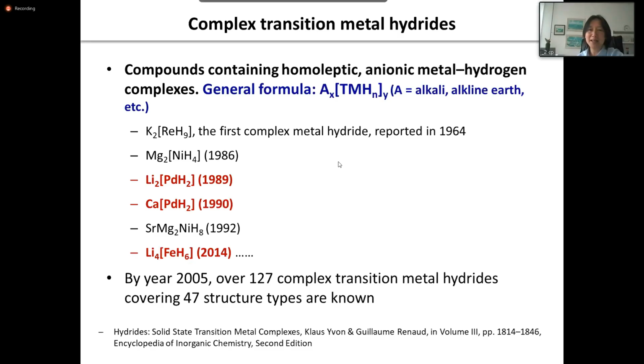I also would like to bring your attention to the lithium palladium hydride. It was reported in 1989. In this hydride, you will see that the palladium is in 0 valence, but hydrogen is covalently bonded with palladium, and they form an anion. So this could be, I think, the very first palladium hydride, if I remember correctly.